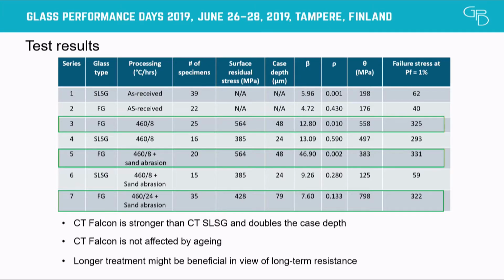But interestingly enough, and this is already known in the literature, the surface residual stress decreases its value. What does this mean? Honestly speaking, the resistance of this material is far more than we need. So it will be more interesting for us to have a longer treatment with a larger case depth for some applications.